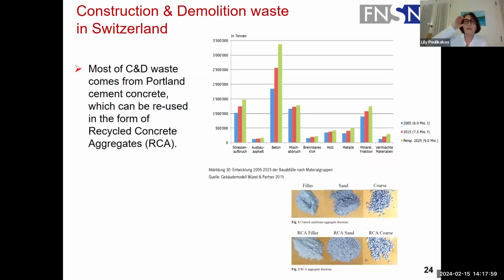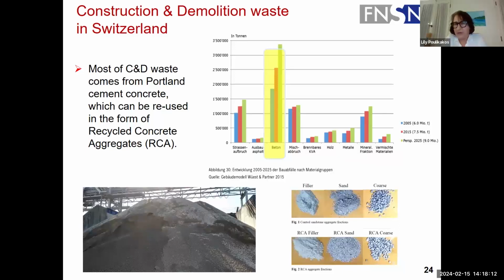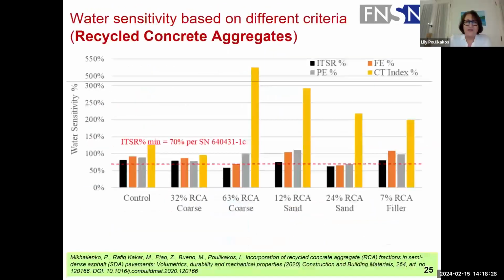So I'm moving now to another material. Most of construction demolition waste comes from Portland cement concrete, that in German is called Beton. You see here the amounts of the different contents of construction demolition waste. Also in the lower part of the slide, you see the different fractions. We have added the construction demolition waste with different fractions of it to our mixture, or we replaced the different fractions in our mixture. In black, you see the ITSR, the conventional ITSR, and we've also used other methods for water sensitivity. You see that compared to the control, we also have several mixtures that do pass the requirements.